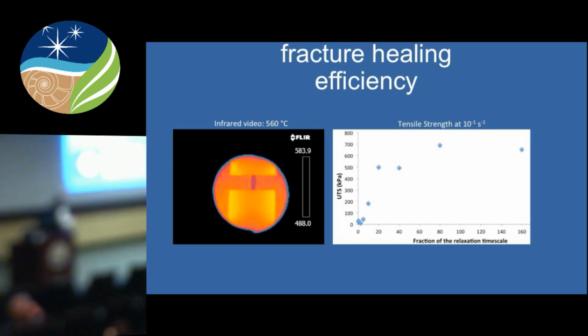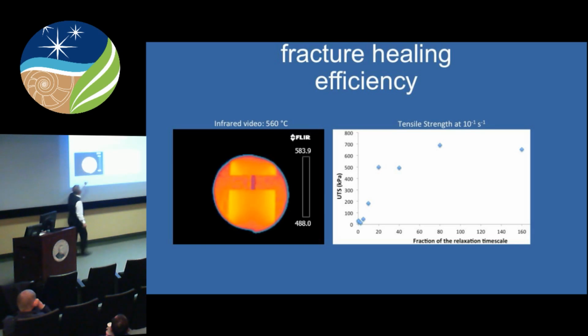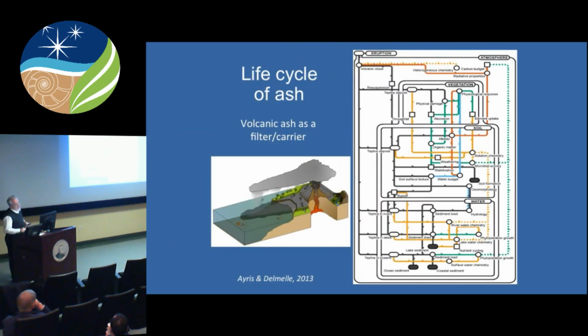If these things are breaking, and if they are still high temperature liquids, will they seal again if we stop moving them? In other words, can there be a cyclicity to all of this, which also might produce its own seismicity? And this is again measurements from Liverpool, where you're cyclically moving up and down two large blocks of volcanic dacite and increasing the contact time, and as a function of increasing the contact time, measuring the force which is needed to pull them apart again. In other words, how do we seal, how do we heal these things? How much time does it take?